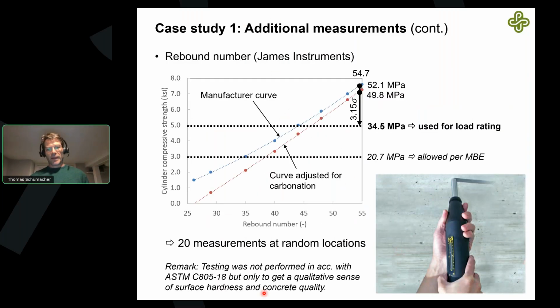Rebound number, I want to make it clear here that I'm not suggesting that you should take rebound measurements and convert them to strength, but what we wanted to see here is, per the manual of bridge evaluation, we were only technically, without any measurements, you can, and if there's no drawings available, based on the age, you're allowed to use about 21 megapascals for concrete strength. We did these measurements, we distributed them across the bottom, we converted them with the manufacturer curve to strength. We found some research that helps us adjust for carbonation because that skews the measurements.